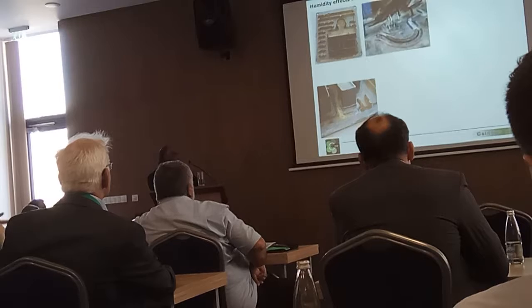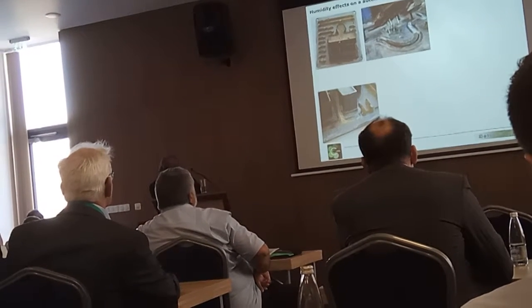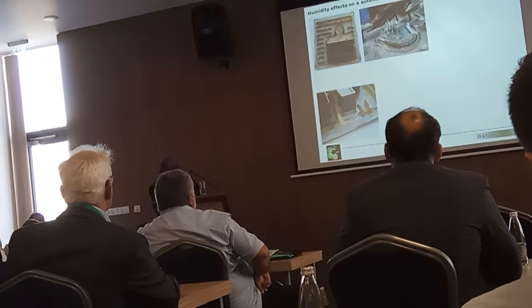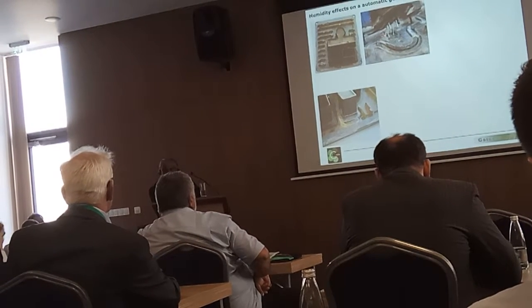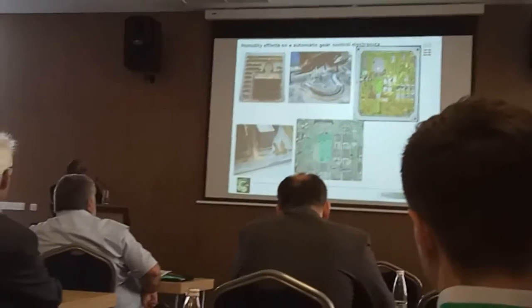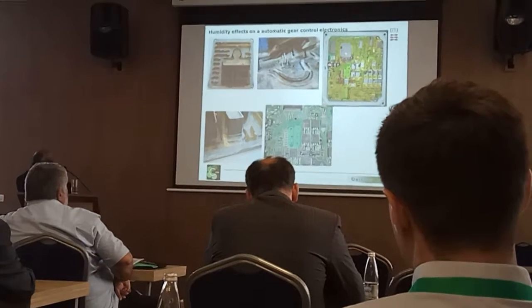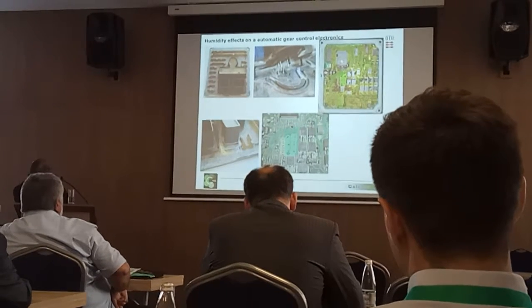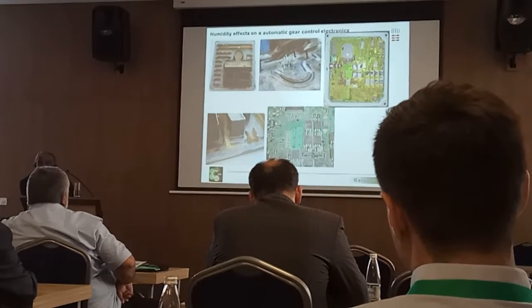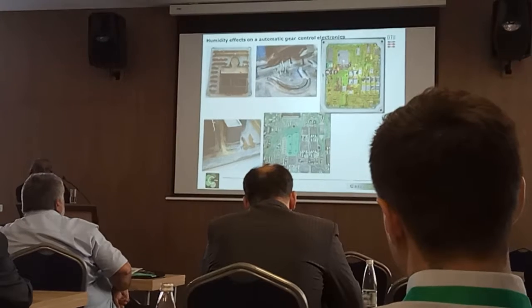To impress upon you this point — this is an automatic gear control electronics for a car. It had very good encapsulation, meaning it was enclosed very nicely, but after a long time, the O-ring failed, and that allowed humidity to enter into the electronics. Because of temperature fluctuations, it caused condensation on different parts of the electronics. Many of these places show corrosion, which you cannot see by naked eye, as I mentioned — by the time you open the device, everything has disappeared. You can see it here because we applied some indicator gel onto the surface, and the gel highlights the corrosion. The magnified view shows all these capacitors had condensation on top of them, which created a leakage current, and in some places it also created some electrochemical migration, leading to failure of the device.